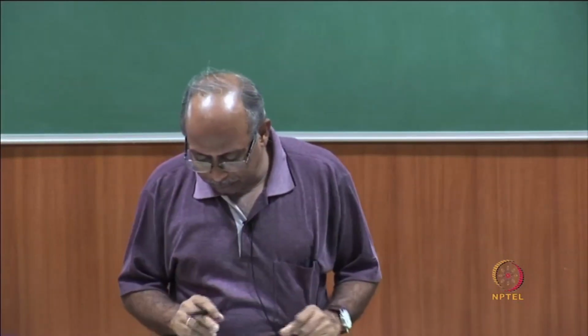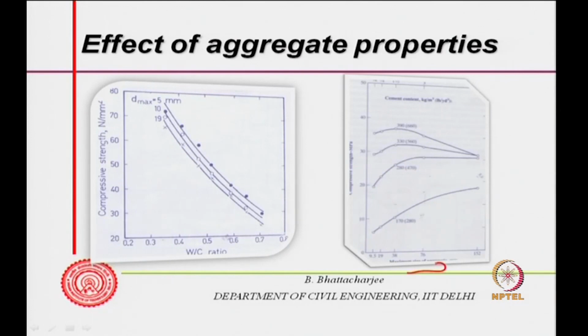So, what has been observed is that if you go on increasing MSA along this direction, for low cement content, strength increases as you increase the MSA, and then it does not increase further. Here the strength increases and becomes constant, and at high cement content strength increases and then starts decreasing.